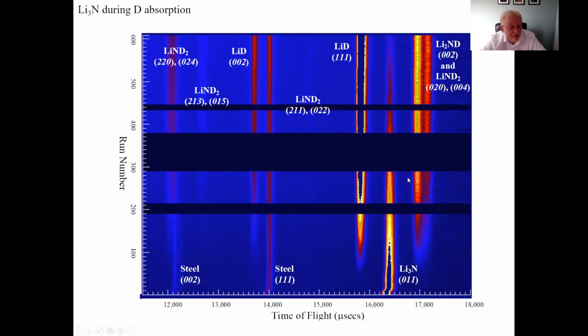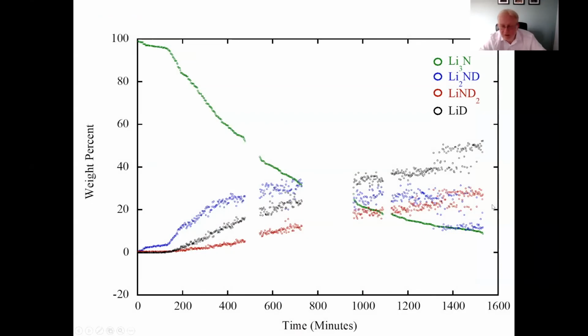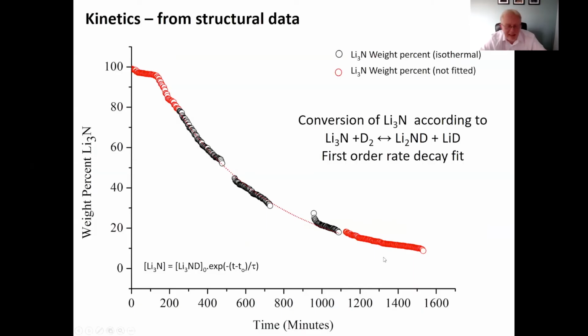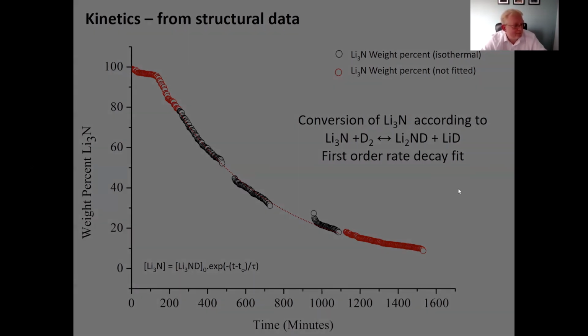But you can clearly see you've got a phase transformation as the lithium nitride disappears, lithium deuteride and lithium imide is formed, and that will eventually go on to form lithium amide, which is just coming in here. You can use that Bragg information to plot the phase transformation of these phases. You can see the lithium nitride phase is decreasing and the other three phases are increasing in intensity, and you can plot that and calculate the kinetics of those processes. This is just an Avrami fit that Bill David did.